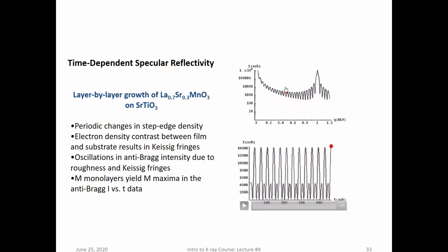But what you see up here now is all these little fringes. These are the fringes, this is the sine squared nx over sine squared x. These are all my intensity fringes. This is the thickness of my thin film, so I can just measure that.